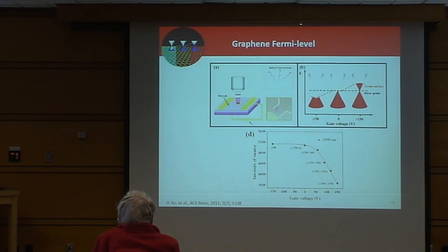We also studied the graphene Fermi level as a factor in the GERS effect. We apply an electric field to the graphene, and we can change the Fermi level of graphene. What we found is that the intensity of the molecular Raman signal changes with the applied electric field.